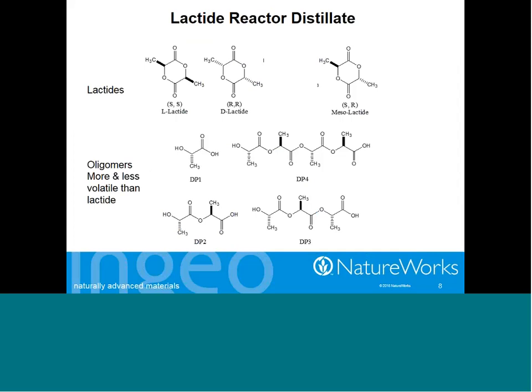And this next slide is again, sort of the chemistry of the lactide distillation. Ideally, there would be no chemistry going on in that process because of the presence of the alcohol groups in some of the oligomers. It is a reactive distillation, but over the years we've learned how to tame that. What I've shown here is kind of the split of enantiomers, the SS and the RR or L and D lactide. Those are enantiomers, so those are not going to be separated by the distillation process. Mesolactide is a diastereomer of both of those enantiomers, and with that big column that I showed you on the third slide, we can separate efficiently mesolactide from the two chiral species, the L and the D.